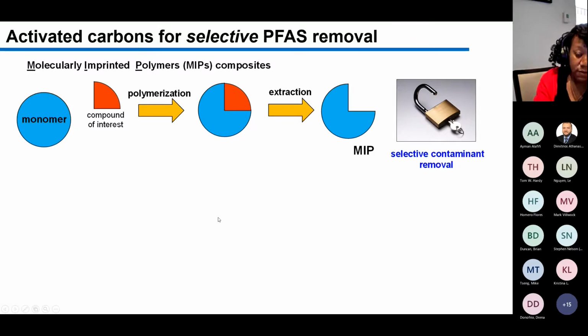So what we're doing is, I should back up. This has been done for the last, like 80 years or so, and it's been used for applications like detecting certain drugs within mixtures of drugs in solution. It has also been used to remove contaminants in water. So if you want to target compounds like PFAS or other organic compounds or inorganic compounds, there are versions of this material that have been very well studied in the literature. The problem is when you do this type of polymerization, you end up with a very fine powder. So that's not something we want in, let's say, a stormwater infiltration system, because that'll just get washed through and then you might not even get removal of the contaminant that you're hoping to remove in that case.